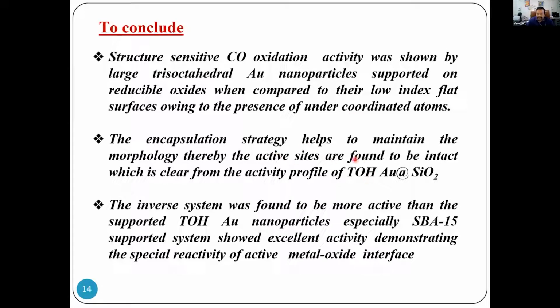And encapsulation also helps to maintain the morphology and stability of the nanoparticle, which means that the active sites are intact, and then it gives a stable conversion throughout the temperature regime as well as the time on stream under which you run these experiments. The inverse systems are found to be active because you create more metal support interface, which facilitates the activation of oxygen at these interfaces.